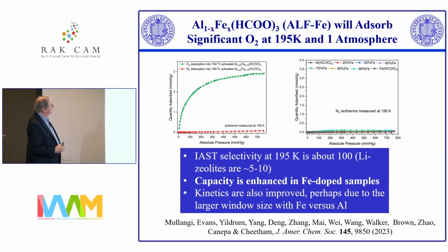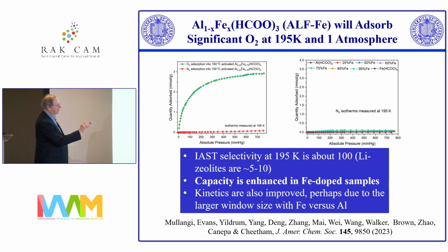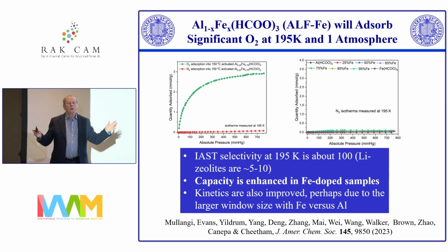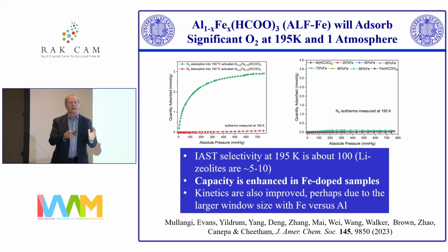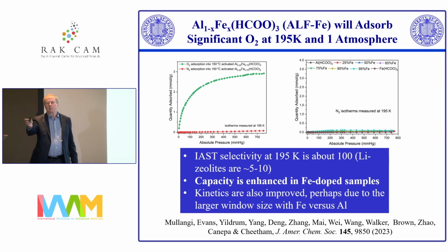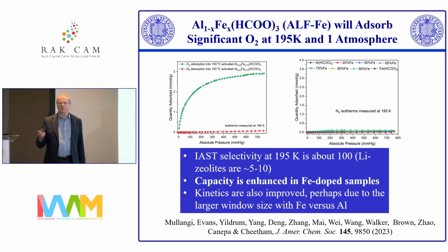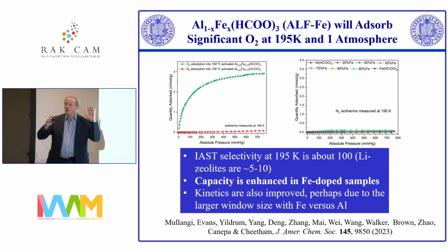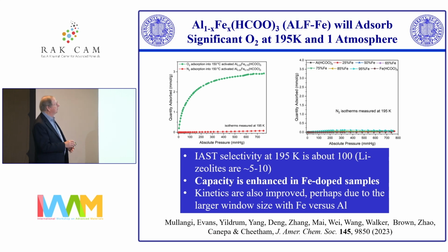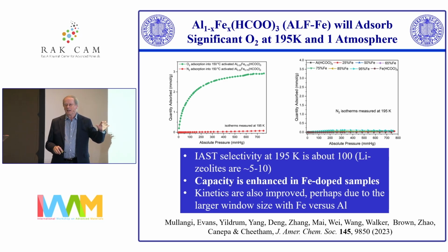So that's not ideal, but under those conditions, there's no nitrogen being adsorbed at all. This is the nitrogen adsorption isotherm. And so initially I was satisfied with that. I thought, well, we could actually potentially commercialize this, and all we need is dry ice, and we can do it easily at 200 Kelvin. And then I went to India and discussed it with Pratap and Professor Diwakar in chemical engineering at the JNC. He was interested to do this because they have a small startup doing this kind of thing. But he said, we don't want to be cooling it. We don't want to be going to villages in India where they need oxygen and cooling it. So can't you do it at room temperature? So we since then have done that. We've not published it yet, but we just filed the patent a couple of weeks ago. And so we're ready to publish it.